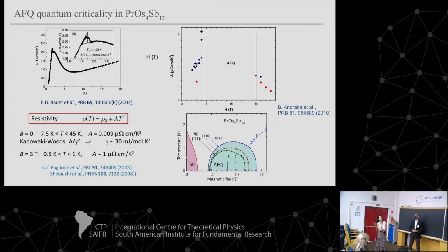There was some discussion that maybe there is quantum criticality associated with this antiferroquadrupole phase, and there's a little bit more over here, but not so much. We also measured with de Haas-van Alphen oscillations and could measure the effective mass, and it doesn't change very much. There's a very weak enhancement going across the antiferroquadrupole phase, but the more dramatic behavior is at high field where the mass takes off. So I would say there isn't a huge signature of quantum criticality in this system, but that fits with our picture, because we think the nuclear degrees of freedom are suppressing the electronic quantum criticality, which gives a reason for not seeing very much in the physics. People were wondering why there wasn't dramatic quantum critical behavior, and this could be an explanation. All right, any other questions?